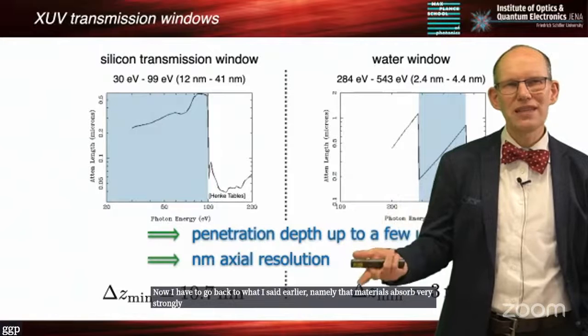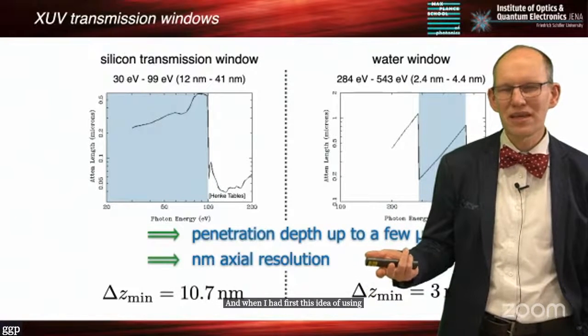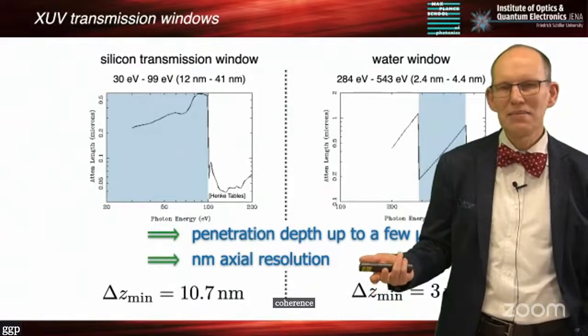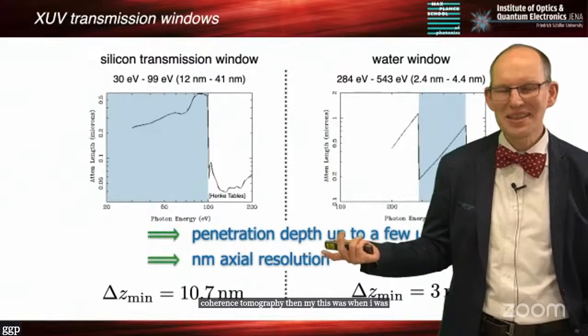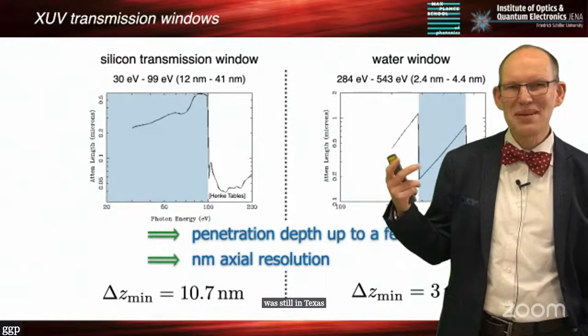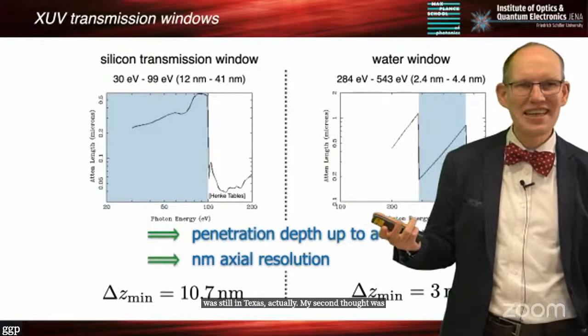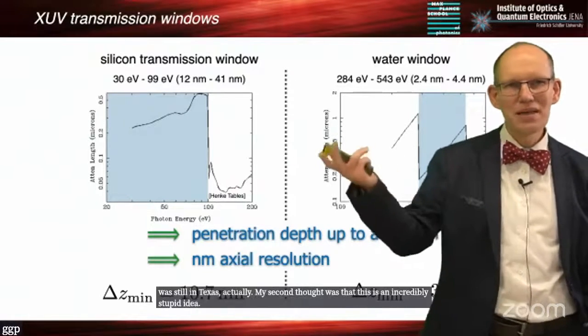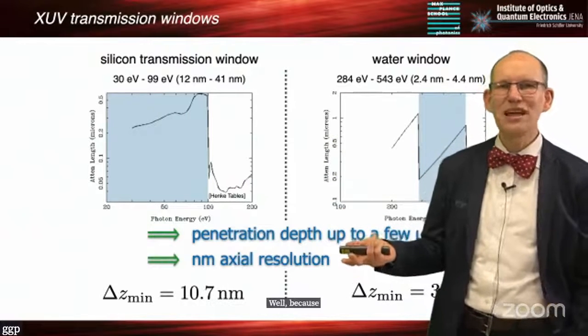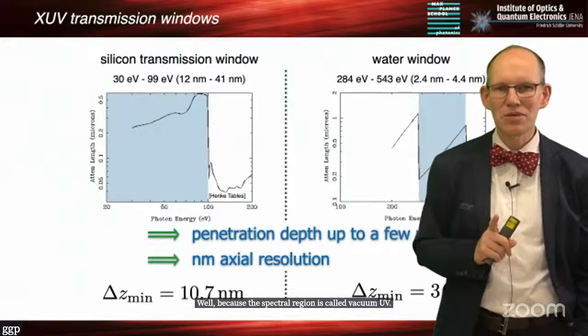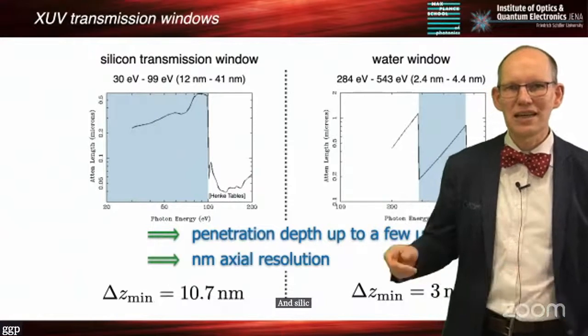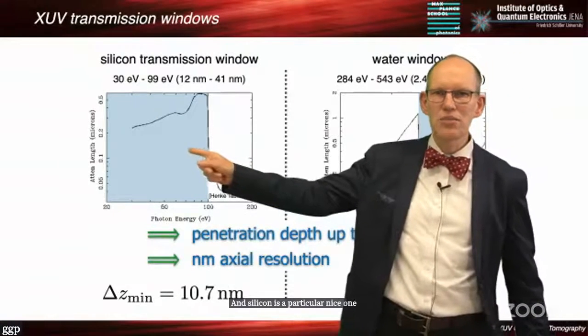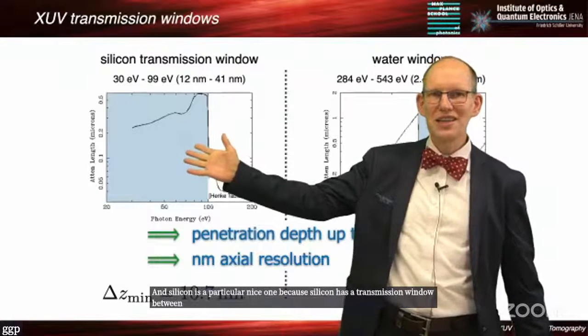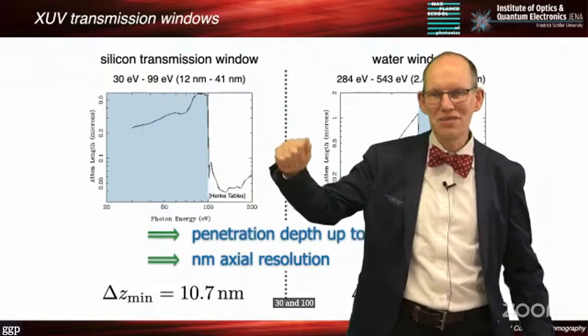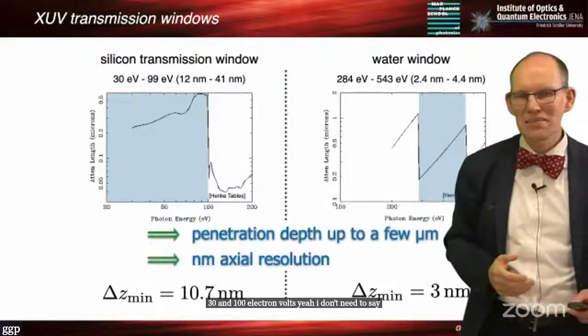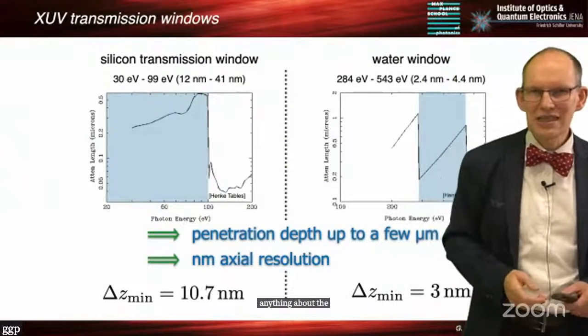And when I first had this idea of using high harmonics for doing coherence tomography, this was when I was still in Texas, actually. My second thought was that this is an incredibly stupid idea, because the spectral region is called vacuum UV. But there are exceptions. And silicon is a particularly nice one because silicon has a transmission window between 30 and 100 electron volts.